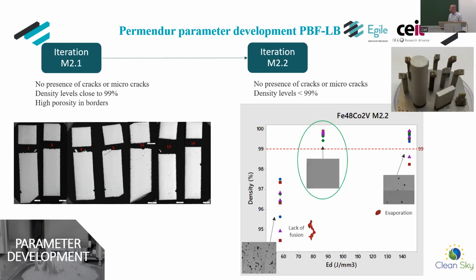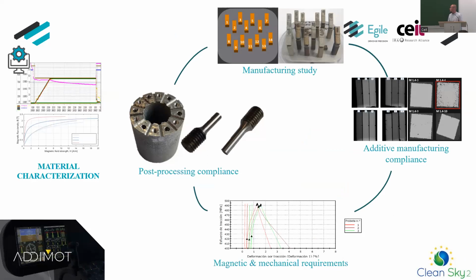Clearly, as was shown before, when using low energy density levels you get lack of fusion. And sometimes when using high energy density levels, you get these round pores, which means that evaporation has occurred during the laser melting. So once we've finished with the parameter development and the manufacturing study, it's time to check the magnetic and mechanical requirements after the heat treatment.